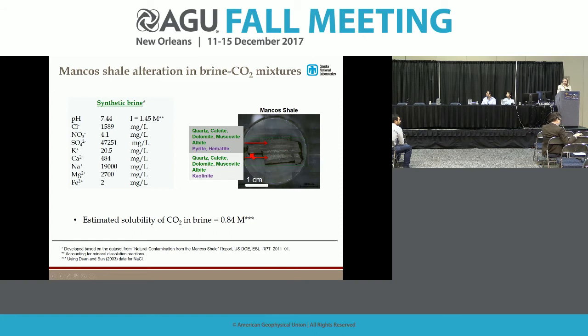Mancos Shale, here I have an optical image, and of course you cannot see because of the light, but trust me, it's really heterogeneous. It has visible lamination. You can see lighter and darker layering. And compositionally, those layers have the same minerals, but at different proportions. And I'm going to show you later what those are. And we took an unconventional approach. We're not using a simple brine. Instead of using DI water or 0.1 molar sodium chloride, we actually matched the composition of our synthetic brine to that observed in the field. So hence this crazy brine. It's mostly sodium chloride, but has a significant amount of sulfate, which is characteristic of Mancos Shale and has been reported in the field. And for this brine, the expected solubility of CO2 is 0.84 molar.